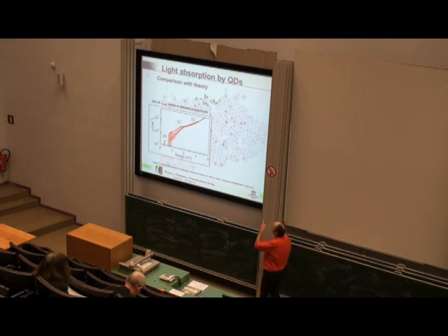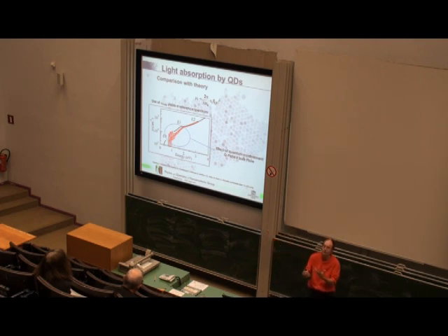Something we do know is this epsilon for the corresponding bulk material. And so we can use this formula to calculate the kind of reference value, the absorbance we would have if this small nanocrystal were just a bulk material. And that's the black line on the curve. And so you see where we have these quantization effects, there's a clear difference between the bulk material and the nanocrystal. This is this confinement of the electron, the change of the energy levels.